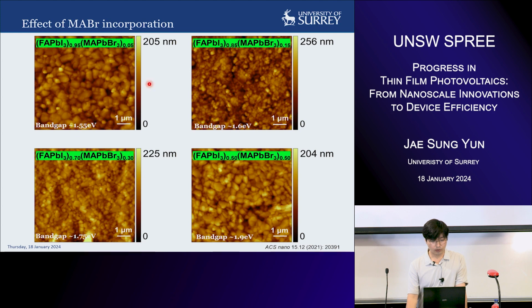The microstructure wise, we took these materials for AFM analysis, and you can see when we put 5% of bromide, this is how the topology looks like. The grain size slightly reduces when we put a bit more of bromide, 15%. And there isn't much difference between these two when we put 30% of bromide, and we can see that even grain sizes get larger when we put 50% of bromide, which gives us around 1.9 eV.